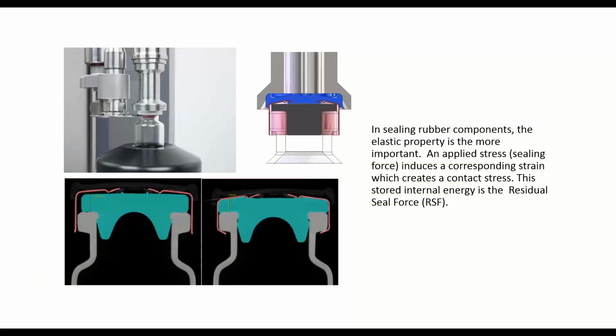So in sealing, and this is just a representation of one sealing type of several, here you see a vial that's held in place, and a pressure block or plunger comes down that pushes down on the top of the vial, and that compresses or squeezes the rubber. In this case, a sealing disc or roller comes in and crimps the metal while the rubber is compressed. The two X-ray images you see below show that. You see an uncompressed rubber stopper with the aluminum seal, the aluminum is in pink here, and how that fits over the vial, and then what it looks like after the sealing process. So you can see some significant viscoelastic deformation there.